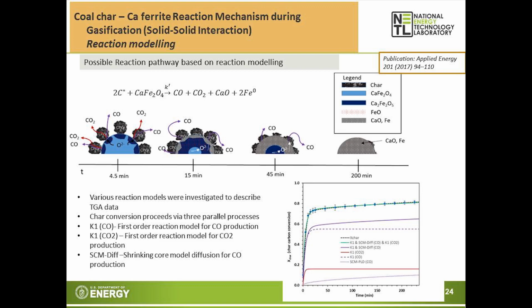So the steam enhances the hydrogen production. Then we did some reaction modeling. We took various reaction models that are in the literature and investigated these models to describe the TGA data. From the analysis, we found that the char conversion using calcium ferrite proceeds via 3 parallel processes, as shown here in this graph. The carbon monoxide and CO2 formation initially followed the first order reaction model, while the shrinking core model with diffusion is responsible for the carbon monoxide production later.